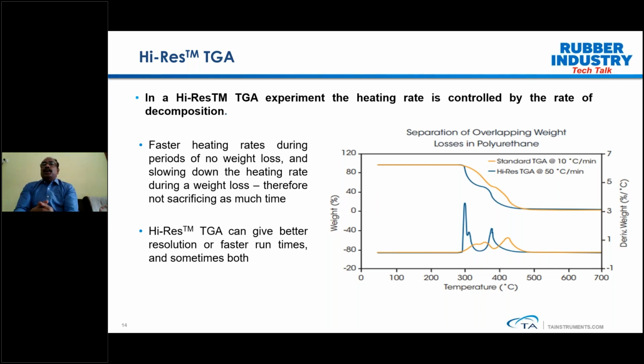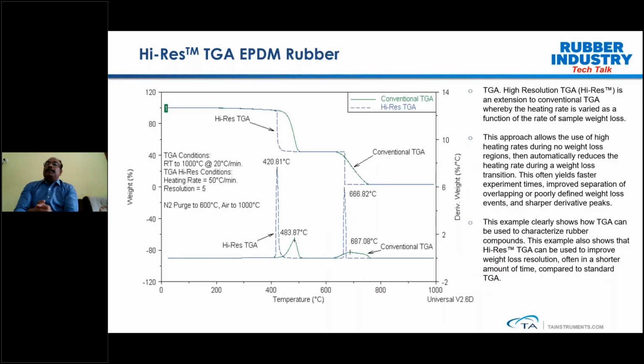Now, I could show you a simple EPDM rubber curve high-res TGA part. So this is again what you can see here. The green curve is a conventional TGA where you'll be heating at a standard ramp rate of 20 degrees centigrade per minute. Coming to the blue curve, which is high-res TGA, you can see the derivative peaks look very sharp, and that is because of a better resolution.